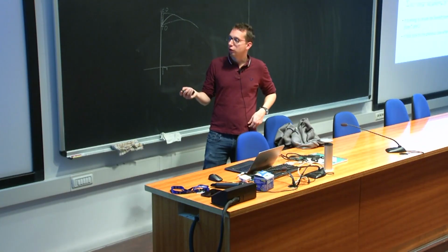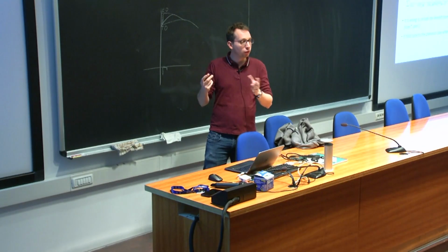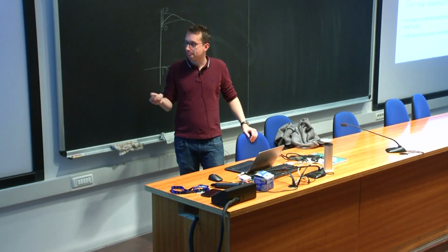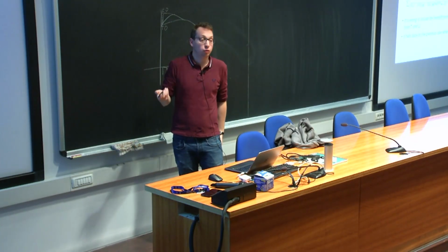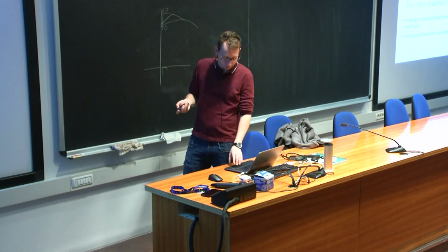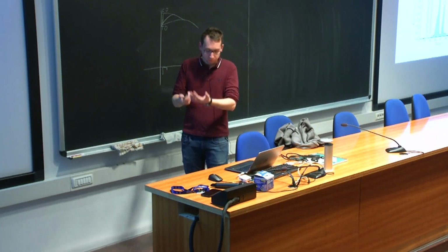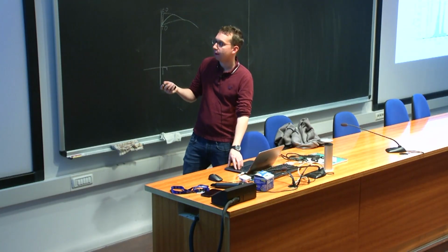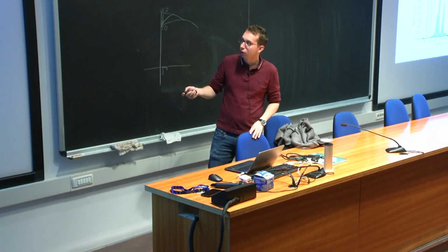What we have done in some works is to treat it with some stochastic sampling of the position of the atoms. Other people do molecular dynamics and then extract it by fitting or by doing velocity correlation. Or you can just do finite differences if you want, of the phonons or the forces or whatever else. But once you have the shifted phonons and you get the imaginary part, you can put it in a formula, and you can get this, a spectrum of palladium hydride as a function of the energy.